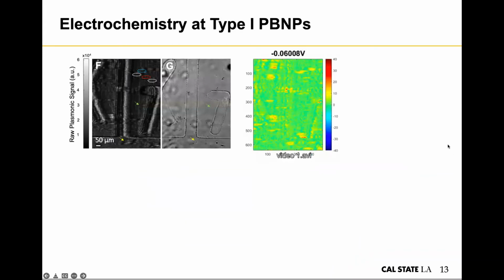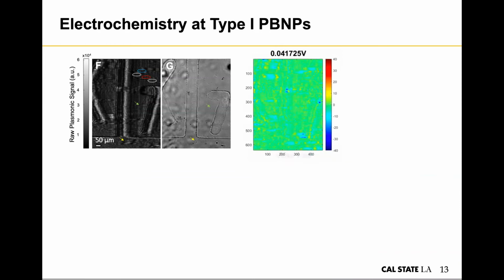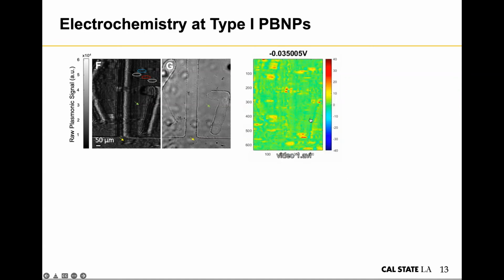This is the first example where we used PEM for the type 1 Prussian blue nanoparticles. As I said, this one has no PVP, so the product is more random. And specifically in this example, we used gold chips that were etched with some patterns, so it makes it easier to later correlate the location of the particles. And here's a video of the PEM images, in which you can see the particle spots, which give us the Prussian blue to Prussian white electrochemistry.